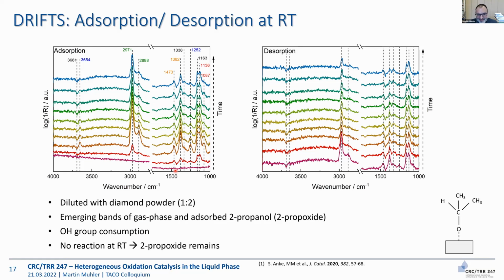Now the question was, can we learn a bit more about carbonaceous deposits? As it's a bit, yeah, not satisfying intellectually. Coking is well established, but you would like to know more about coking. And so we used diffuse reflectance infrared spectroscopy. The IR data are not that nice, but these are all black samples, and it's quite an effort where you have to dilute carefully with diamond powder to get spectra at all. So that was quite challenging to get this data.